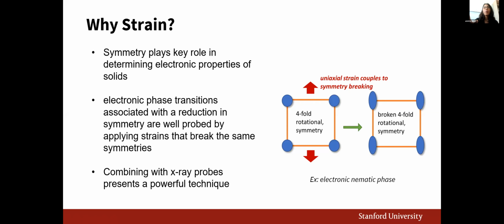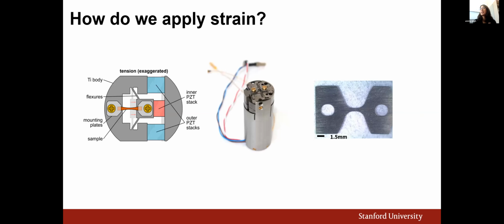So practically, how do we actually do in situ strain tuning? Generally, we use a class of commercially available strain cells made by a company called Razorbill. They're compact and designed for cryogenic applications, and they consist of a series of piezoelectric stacks to which we can apply voltages to dynamically change their extension or compression to apply both tensile and compressive strains.